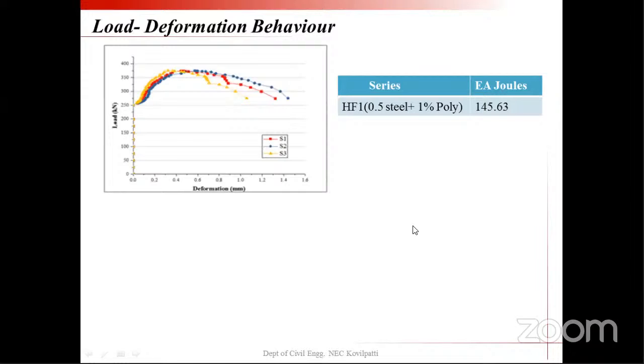And we plotted some load deflection behavior for various series. For example, the area below the HF1 series for the 3 specimens is reported as 145.63. Normally we have to cast more specimens when doing this type of experimental investigation, because we have to do a lot of trial procedures, and only then can we take the final concluding values. Just by placing the specimen and immediately taking the results is surely impossible in the case of FRC or hybrid FRC measurements, because each and every deflection will alter the behavior of the concrete. So I used to cast 8 to 10 specimens for each series.